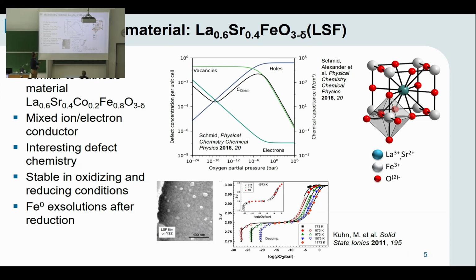Acceptor doping means that we have strontium 2+ on a lanthanum 3+ site. So we have a charge imbalance in the cation lattice. And this is compensated either by oxygen vacancies or by electronic defects, electron holes in oxidizing conditions. And the question whether the material forms oxygen vacancies or electron holes depends on temperature and oxygen partial pressure. And for LSF, this is already quite well understood.